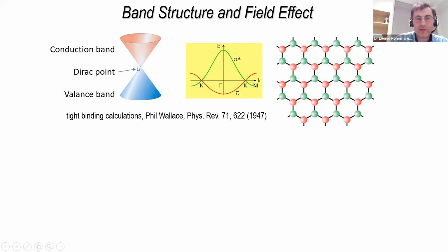So in conventional semiconductors, there is what is called a band gap. So there is a finite energy separation, separating conduction and valence band. And the second huge difference is that these bands usually are parabolic. So graphene was really the first material discovered where these bands were conical. So the dependence of energy on k vector is a linear function, not a parabolic.